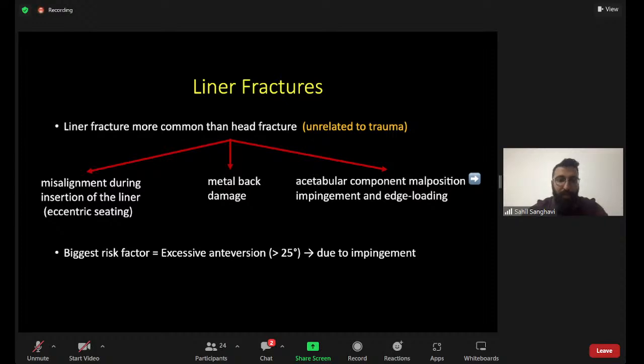Either there is malalignment or misalignment during insertion of the liner. That is, there is eccentric or mal-seating of the liner in the acetabular shell, or there is metal back damage of the shell, or lastly, it is because of acetabular component malpositioning, which is causing impingement and edge loading. And the biggest risk factor for acetabular ceramic liner fractures is anteversion more than 25 degrees. So like I mentioned, ceramic liners are extremely sensitive to malpositioning of the acetabular component.